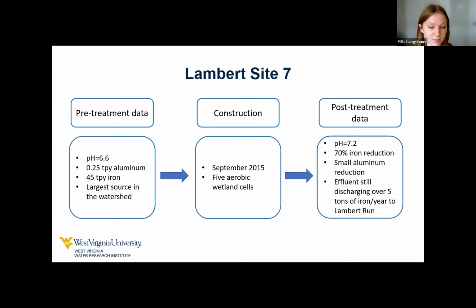So moving on to Lambert Site 7. This is a very large system. Pre-treatment data, we have pH of 6.6, again, relatively high from what I'm used to seeing, but we do see that it was still contributing 0.25 tons per year of aluminum and 45 tons per year of iron. This is by far the largest source in the watershed.